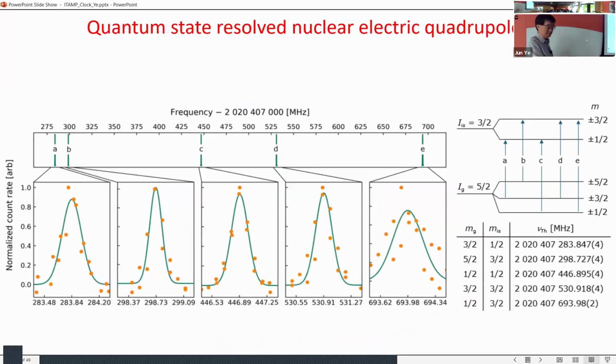But what's exciting, maybe I'll tell you a little bit of the follow-up work. Since we first observed this nuclear transition, the first thing you see is there are 5 lines. There are actually more lines. For the moment, we're focusing on these 5 lines because we can identify them exactly, arising from the nuclear quadrupole splittings of the ground state, which has a nuclear spin of 5/2. The isomeric state, the excited state, is 3/2. You can see these 5 transitions exactly match, and you can apply some rules and so on. In fact, that's the way we found the weakest line, which is 10 times weaker.